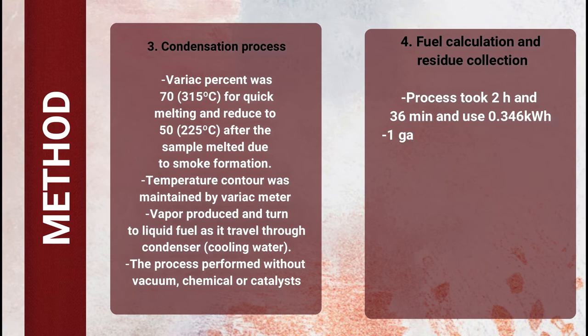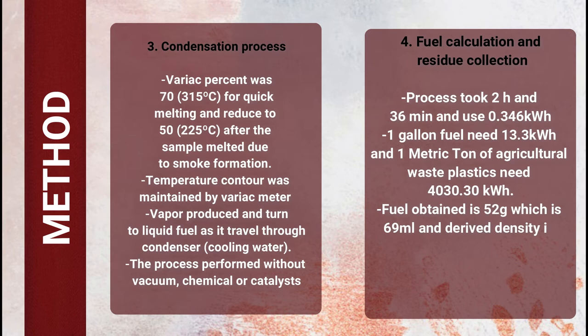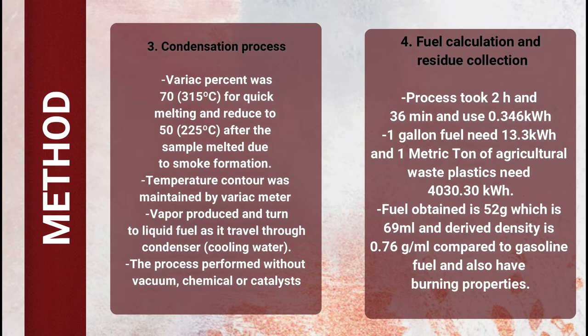The last step is fuel calculation and residue collection. The process took about two hours and 36 minutes and used 0.346 kilowatt-hours. One gallon of fuel requires 13.3 kilowatt-hours, and one metric ton of agricultural waste plastics needs about 4,030 kilowatt-hours.